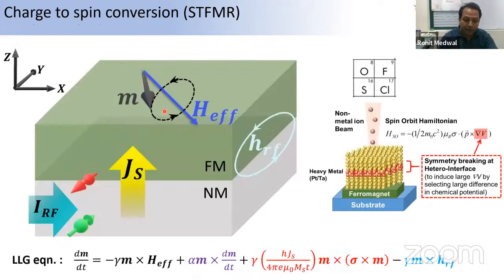And so as I've shown you, the conversion efficiency for the platinum is only 5 to 7%. Can we improve this conversion efficiency in the platinum? So for this, we designed this new material. We try to implant the material, heavy metal, platinum and tantalum.